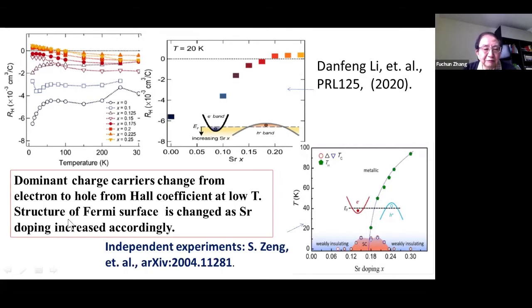And actually the Fermi surface structure also changes as the strontium doping increases. There is an independent experiment by Zeng et al., I think from Haihu Wen's group at Nanjing University, which basically gets the same picture as Harold Hwang's group on the two types of charge carriers. That means at low doping the dominant charge carrier is electron, and it becomes hole when you increase doping.